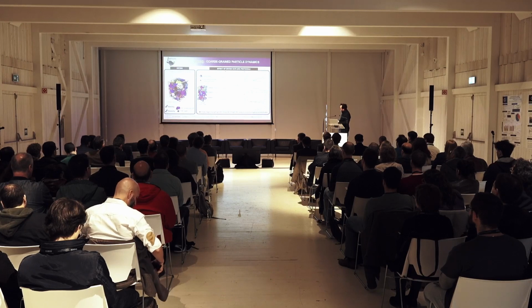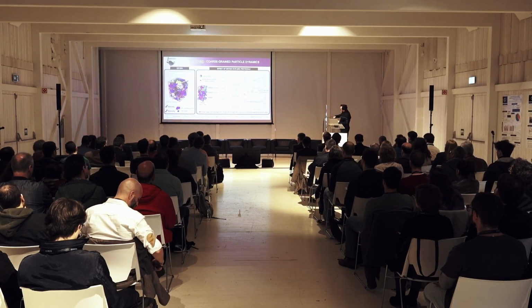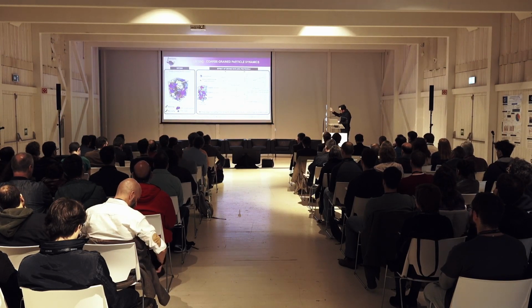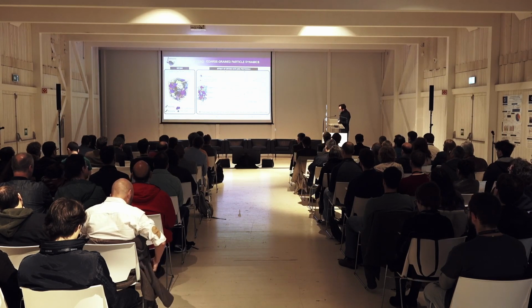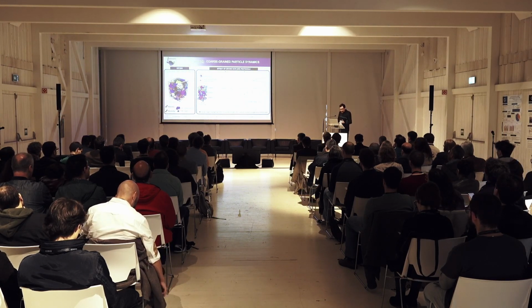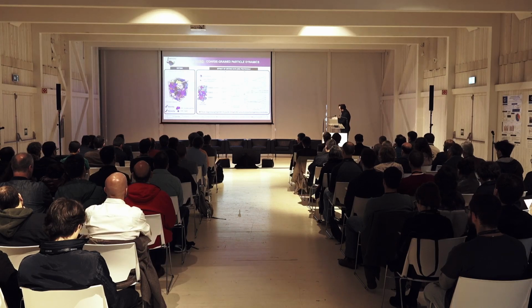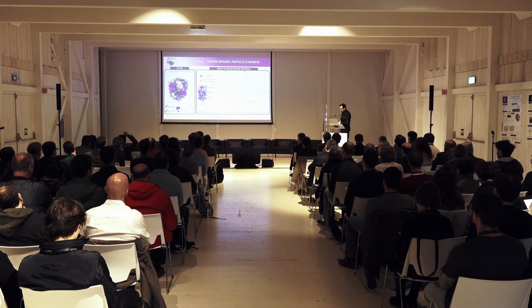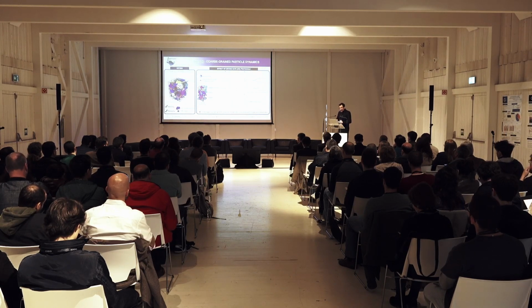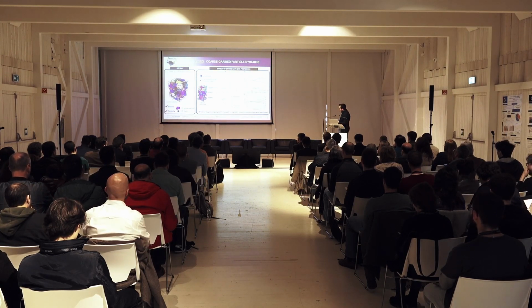Once you get this slurry simulated, you proceed further and you simulate the drying. Okay? In order to simulate the drying, what we do is we shrink the size of these aggregate particles, holding together the carbon, the binder, and the solvent, in order to mimic the fact that the solvent is going away. And then the microstructure converges to a new one that represents the dry electrode microstructure. This dry electrode microstructure can be characterized in terms of a bunch of properties that can also be measured experimentally, for instance, the porosity, the electrical conductivity, and so on and so forth.